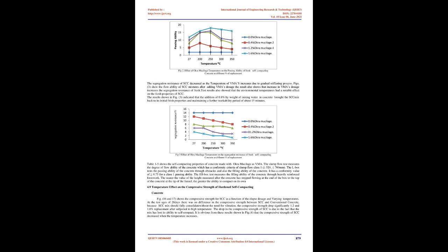Table 6. When the temperature increases, the slump flow and passing ability of SCC mixtures slightly decrease. However, the passing ability of SCC mixtures increases significantly at 0.8% dosage of V.M.A. Figs 1 and 2 show that the slump flow and passing ability at 350 degrees Celsius seriously lost more than that of 200 degrees Celsius.